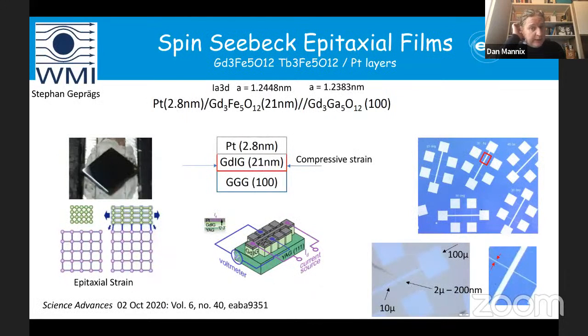So if we look into our material systems, these are grown in the form of thin films. These are thin epitaxial films. So that means they're fully crystalline materials. And in fact, they're very highly crystalline materials. These samples are very, very highly crystalline, very beautiful, high quality samples. They're grown by methods like pulsed laser deposition onto a substrate. So our substrate is this gadolinium gallium garnet, which is a paramagnetic material. And on top of that, we grow these thin films of iron garnet systems.